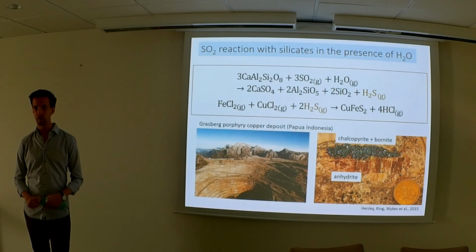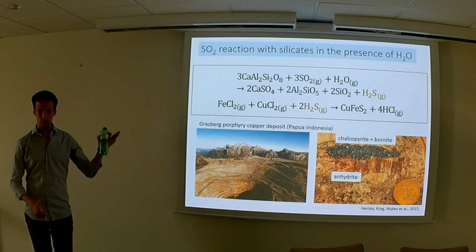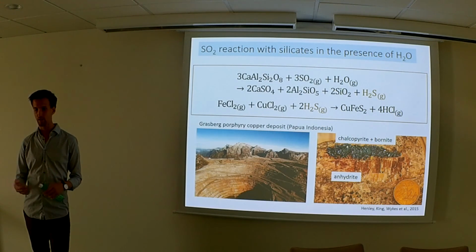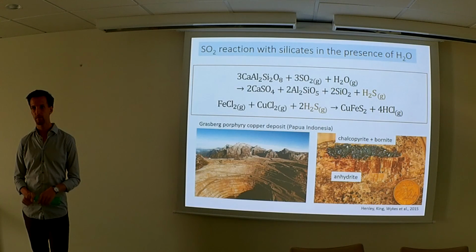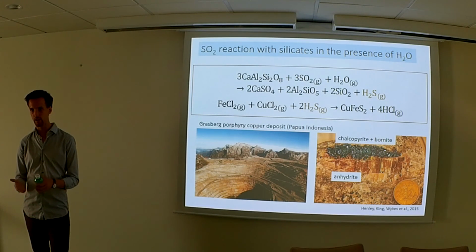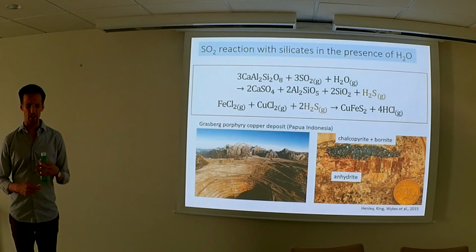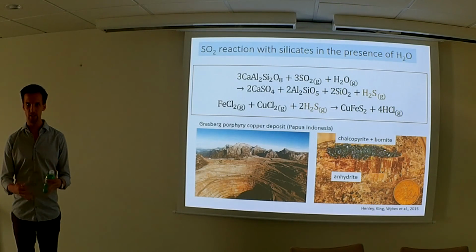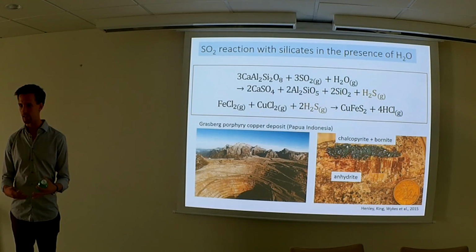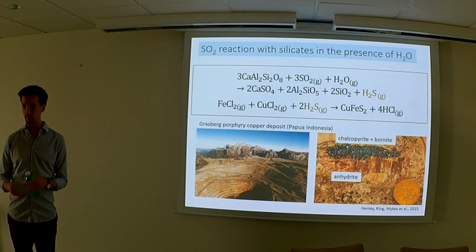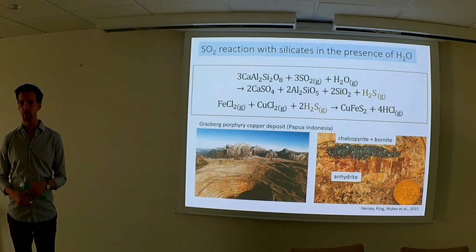The stability of sulfur is affected by pressure, and also by the glass structure and by the way it's incorporated in the melt and so on. So you think in the glass structure it would be 4+, and then it would react on the solid phases. It also has to do with conditions of saturation of the different phases. I think in a silicate melt, it's usually 6+, and then if you release it from the melt, you have a redox reaction releasing it as 4+. So there's an entire other step, which is very interesting, but it's a different story.